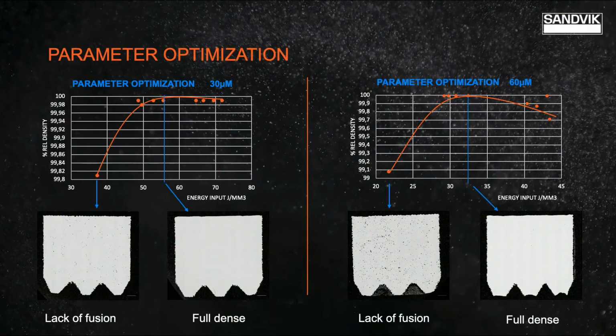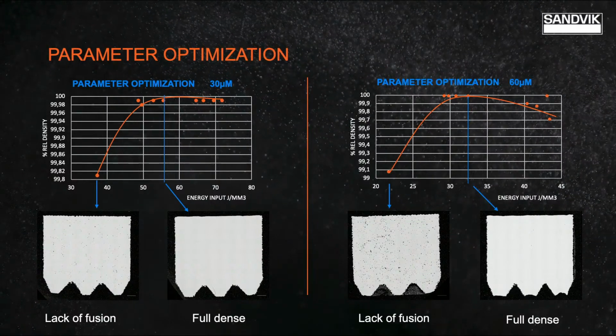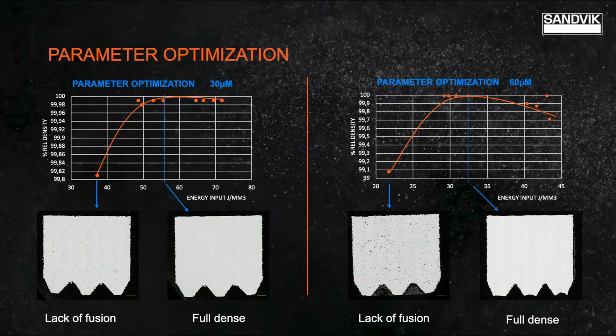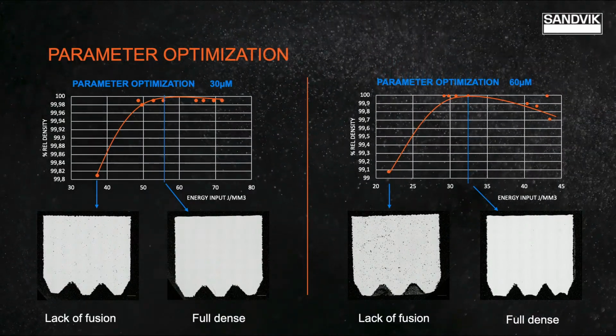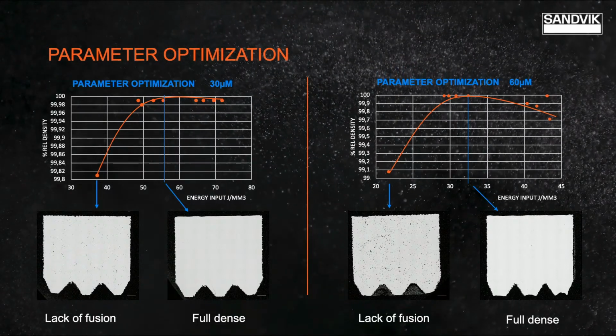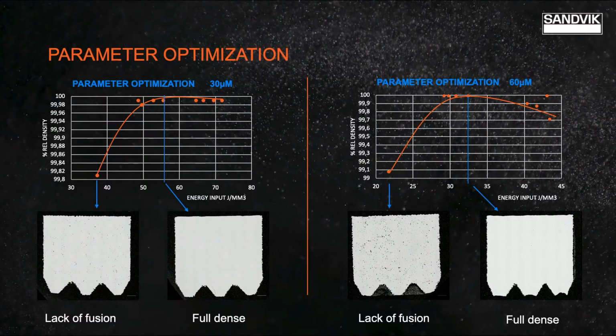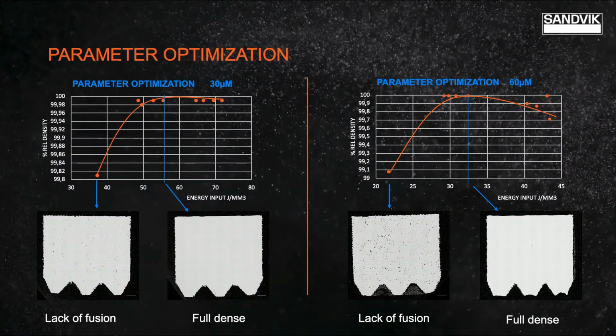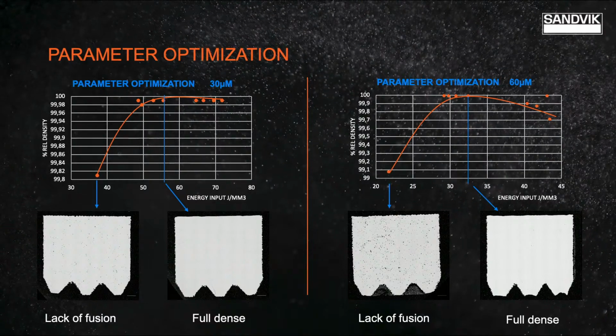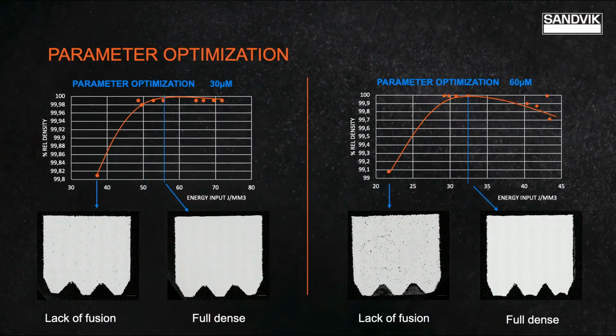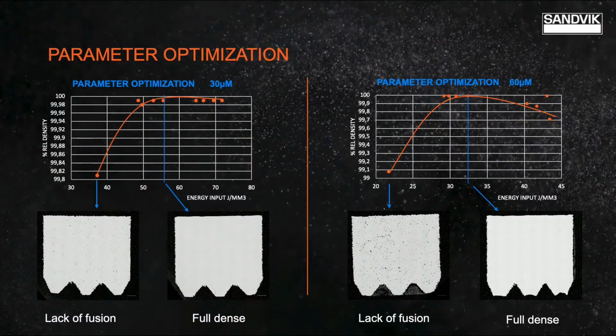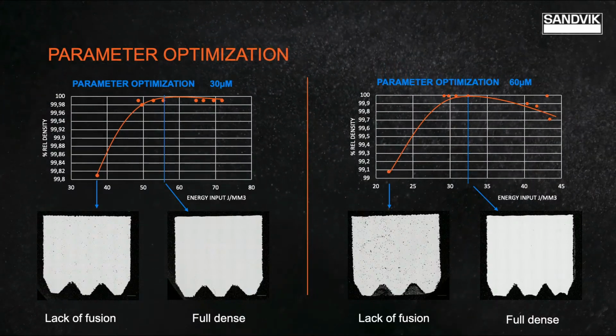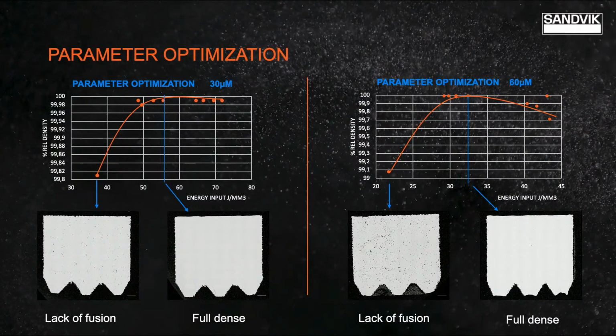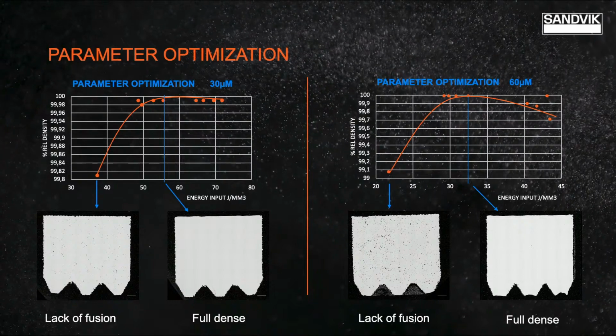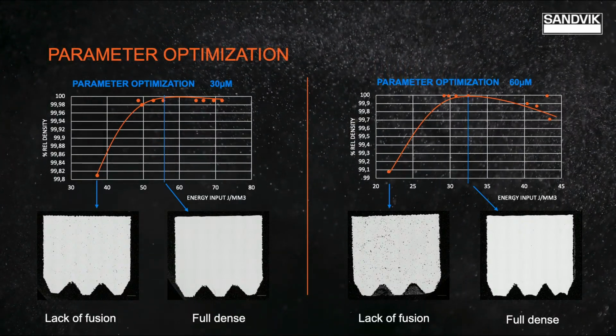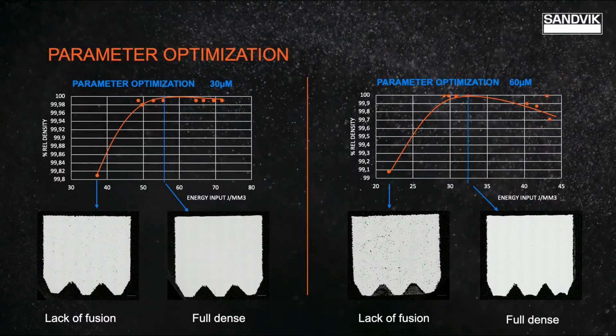The diagram on the right-hand side shows again this sweet spot in the middle section where the material gets very close to full density. You see also a third region to the right-hand side where the density again gets lower. And this is where you get an over-melting of the powder and then you receive gas pores. And that's also undesired. And all these three regions can be seen in the 60 micrometer parameter optimization that you see on the screen. Then I should add that 60 micrometer is of course not the end of the story. We are working on pushing this envelope further and further to drive cost out of the process. The trick really is to produce and tailor a powder that spreads very well and can be melted to high quality, even when optimizing for cost.